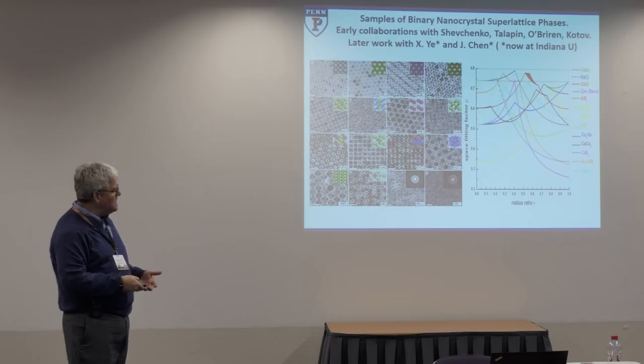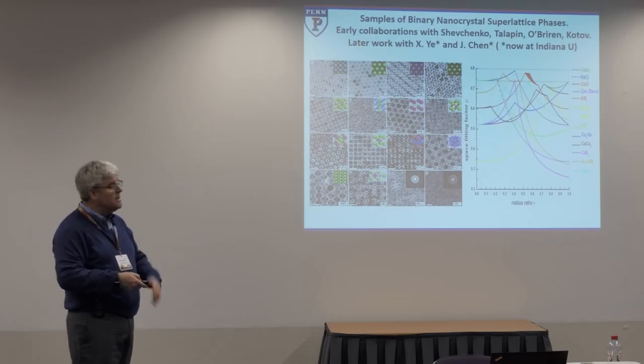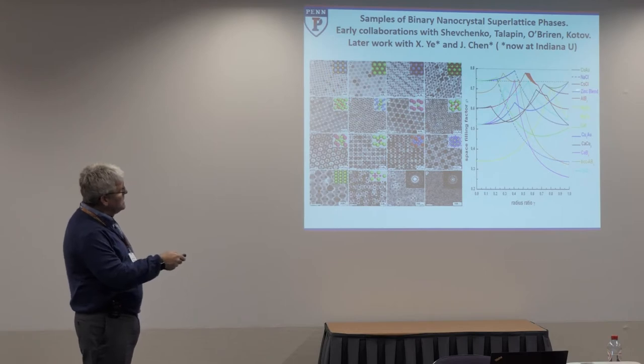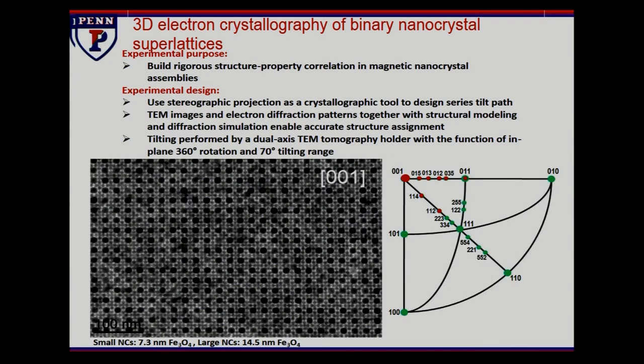So they will be stable against separation just in entropic terms because they can have a higher density than the separated components would have. So things down below that part can be made, and we need to understand whether they're metastable or not, but things that are above this line actually are truly thermodynamically stable. They are the best solution and better than having the separation of the components. All right, so you can treat these materials like you would any other crystalline system. It's just that the length scales now have been stretched out.